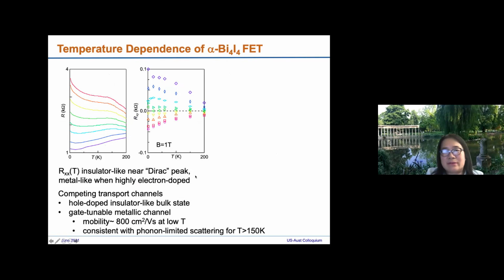Then we can study the temperature dependence of this field effect transistor. The top is close to the resistance peak, and the bottom is highly electron doped. Near the resistance peak, the resistance goes up as we go down in temperature, so this is insulator-like. When it's highly electron doped, it's metal-like, as the resistance decreases as we cool down. The Hall resistance, Rxy, similarly behaves this way, and if we apply the model, we can see how the charge carrier density changes with temperature.